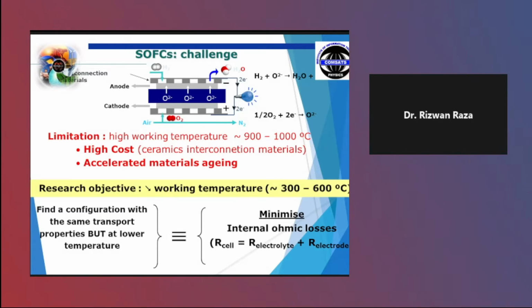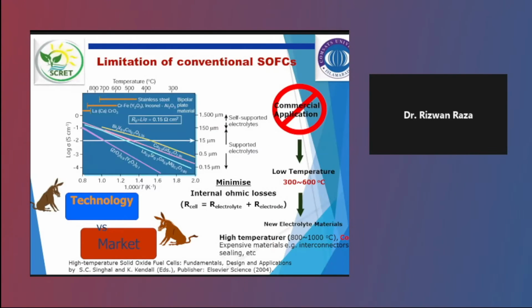Let's say researchers in this area have agreed that if we can succeed at 300 to 600 degrees, then its price can be reduced by almost more than 50%. When we decrease the operating temperature, some materials have challenges, like increased ohmic losses. Some materials are activated only at very high temperatures. You can get more conductivity at high temperature, but when you decrease the operating temperature, its ohmic resistance increases, then its overall performance can be affected and its efficiency can be decreased. So that's why there is a need to find some kind of material which can operate at low temperature.